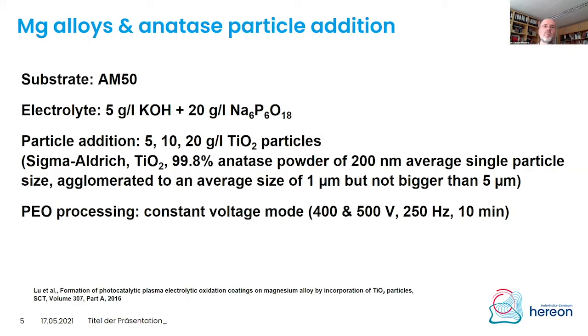So when we are coming now to the first example, how we can functionalize magnesium alloys, I would like to show you a little bit what we did. So basically you use a standard electrolyte, a phosphate-based electrolyte, and we have added here different amounts of titanium dioxide particles to the electrolyte, which is basically anatase because it has the better photocatalytic properties. And we used two different voltages.